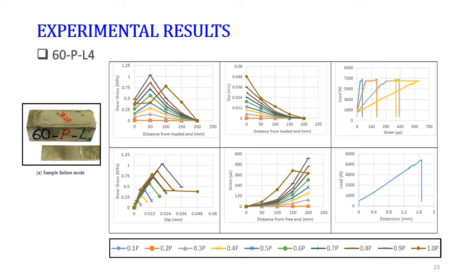And then you have the bond stress-slip shown here, and then we have the strain versus distance, because we have strain gauges that have been mounted on the system and measuring the strain, and you can see the variation of the strains as we go from one point to the other. And the one in the top right shows you the load-strain relationship: when the load is applied, what will be the corresponding strain in the 4 different strain gauges.